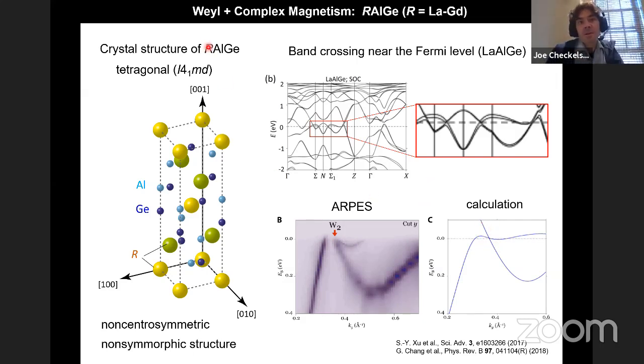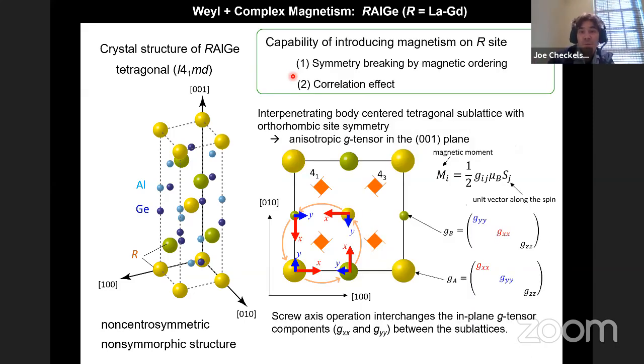But because this is a rare earth system, not only could you put lanthanum on this site, which is non-magnetic, you could use one of the magnetic rare earths. And the thing which makes this system interesting, and I hope the title sort of gives it away, is that not only can you introduce magnetism into this system, it's relatively complicated magnetism in the sense that it sits on a lattice which has a relatively low degree of symmetry. So, to be honest, even when I give a talk in person, I have to use a lot of body language to get across this notion of a screw axis. So this slide might be a little much, but I'll show you the magnetic structure in a moment.